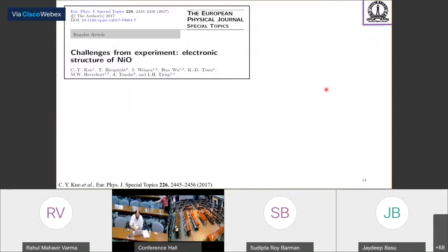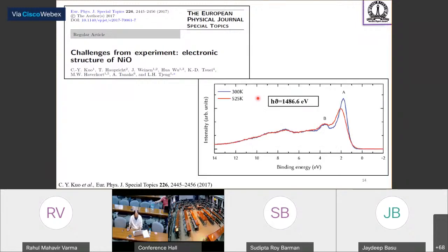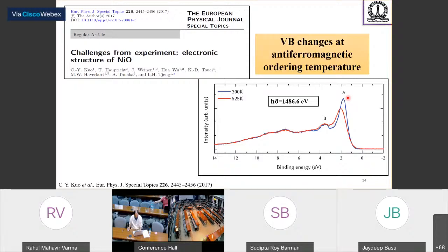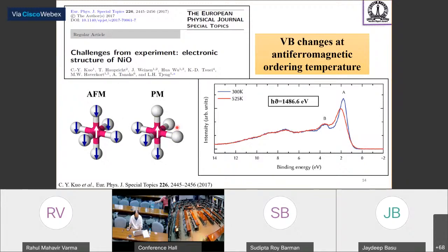In 2017, Kuo et al. performed XPS measurements on nickel oxide and showed that the valence band spectra change at the antiferromagnetic transition temperature, where they collected the valence band spectra at room temperature and 525 Kelvin, which is the exact transition temperature. To explain this, they said that in the antiferromagnetic region, the central nickel atom is surrounded by six antiferromagnetically aligned nickel atoms, but if we go into the paramagnetic region, only three will be aligned antiferromagnetically, and the other three will be randomly oriented. The reduction in this antiferromagnetic ordering, also known as non-local screening, which comes from the nearest nickel atoms, is causing the reduction in the intensity of the main line labeled A.